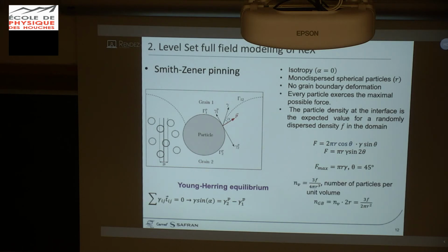But with this main field equation, you can obtain the classical, well-known Smith-Zener pressure of a given statistical description of the second phase particle in polycrystal microstructure. And with this classical Zener pressure, you can also obtain an equation defining a limit mean grain size of the polycrystal during grain growth due to the presence of a second phase particle population.